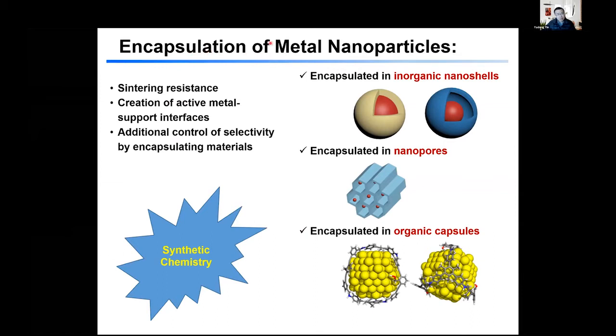We try to develop methods to physically encapsulate metal nanoparticles and then stabilize them. The purpose certainly is to promote sintering resistance, but at the same time, by wrapping these nanoparticles with a support material, we can create active metal-support interfaces, and we also can control the encapsulating materials to provide additional control on this selectivity. So in our review article, we basically grouped the encapsulation methods into 3 categories. One is using inorganic nanoshells, second, nanopores, and third, organic capsules to stabilize all these particles. So I'm just going to go through these different methods very quickly.